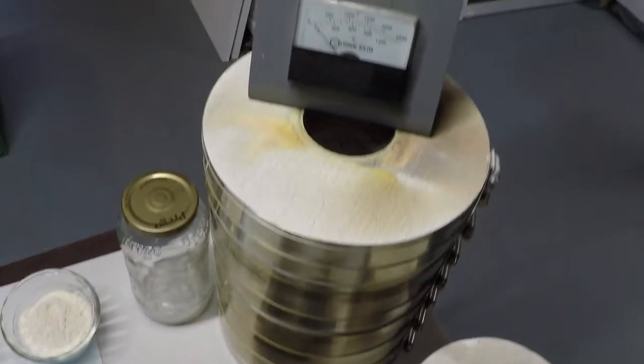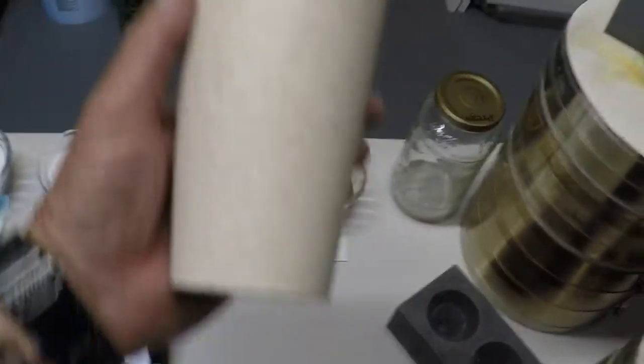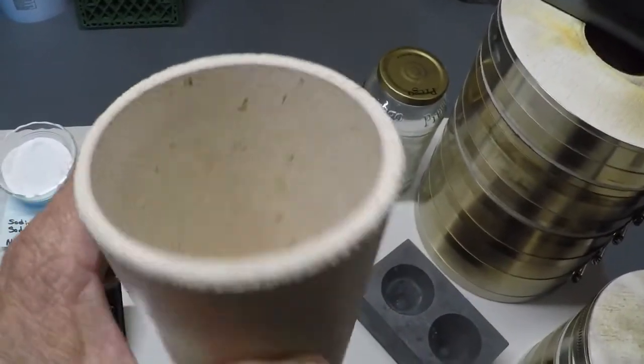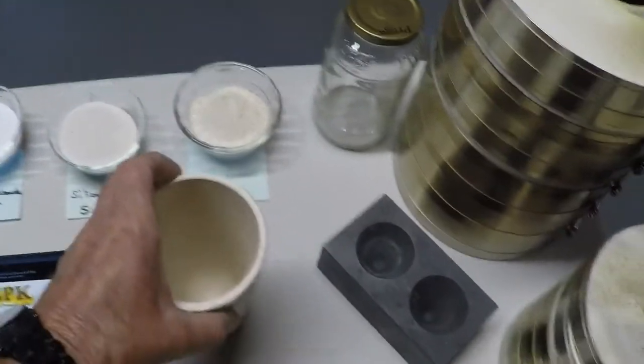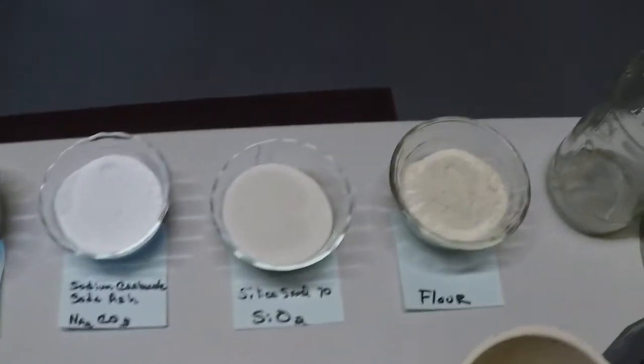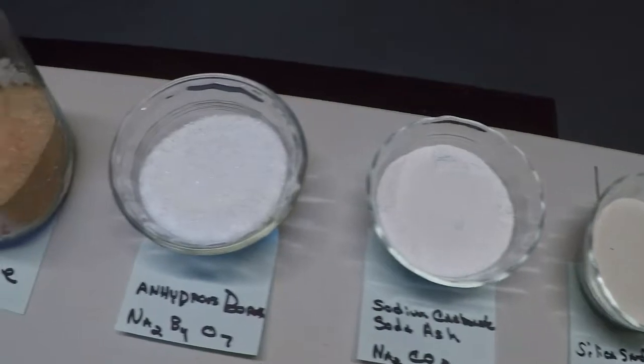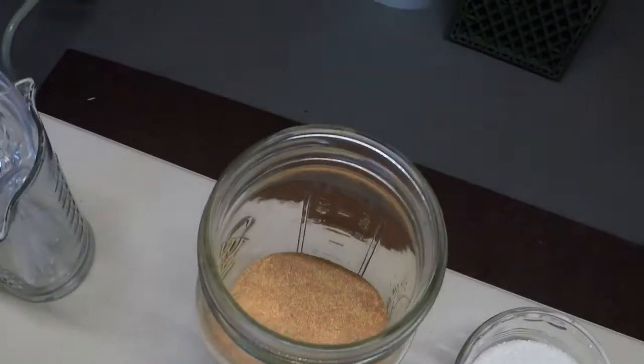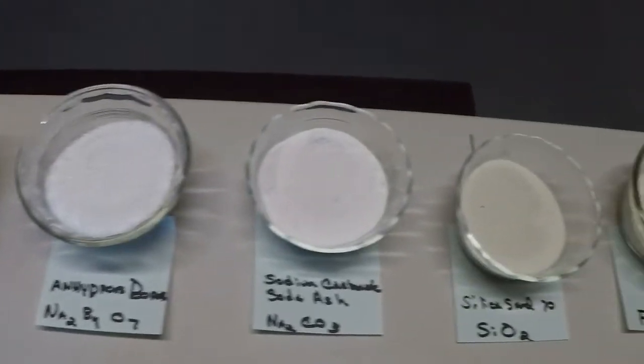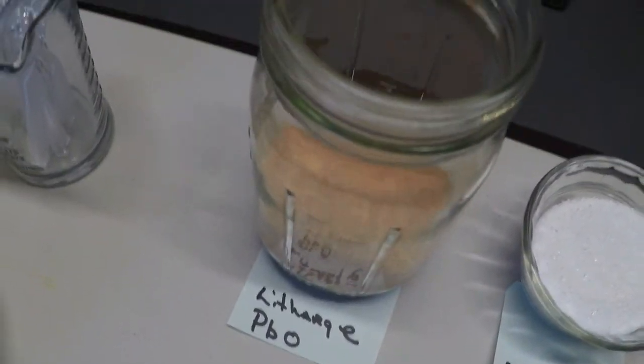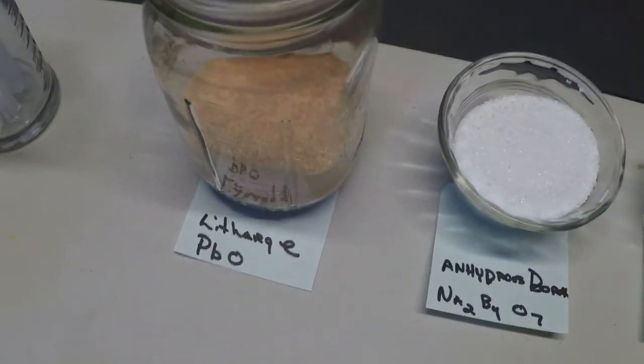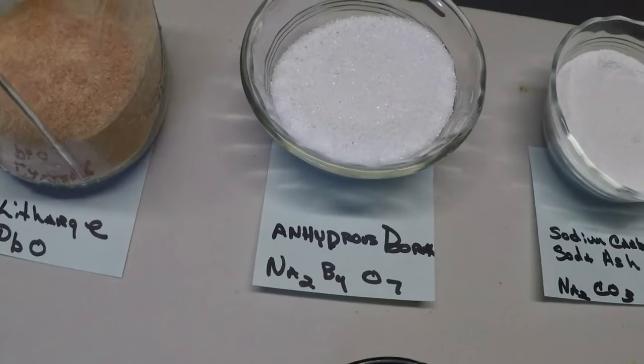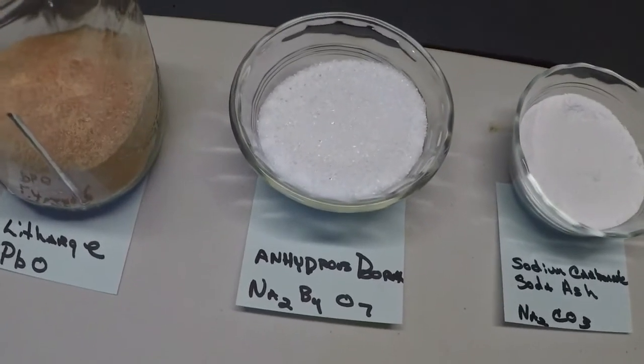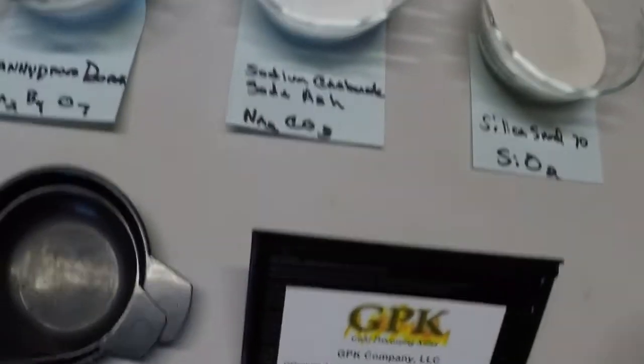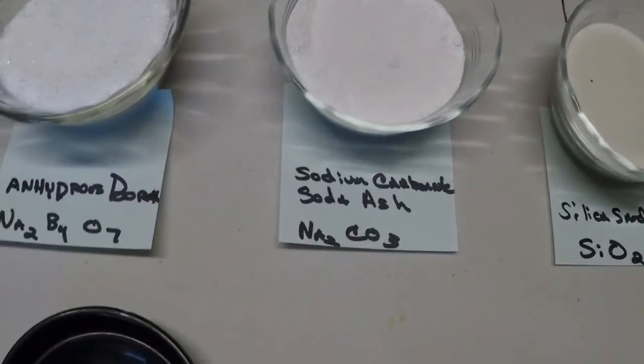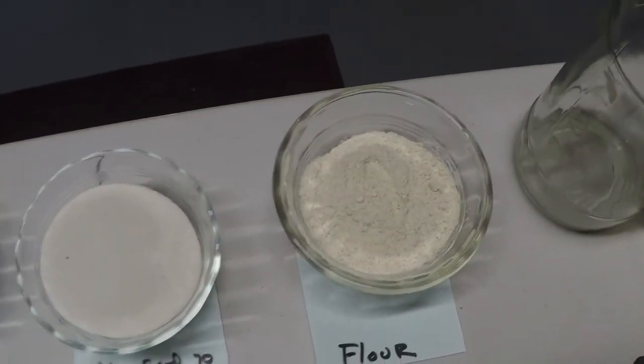We'll put our material in this fire clay crucible, DFC 40-gram crucible. We'll mix all of our ore with our flux here. And I'll reset the camera up when I go to mix all this stuff up so you get a little better idea of what's going on. We have a litharge flux, lead oxide PbO, anhydrous borax, Na2B4O7, sodium carbonate, which is commonly called soda ash, silica sand, and flour.